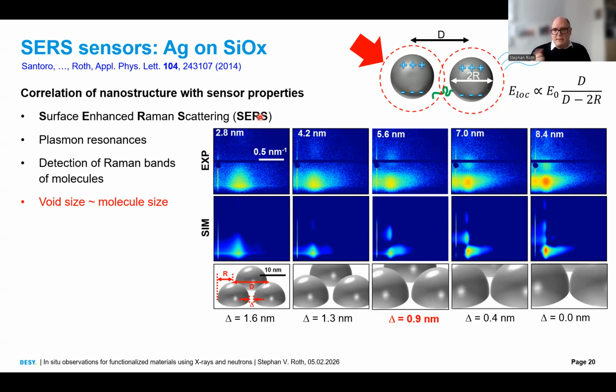And with this experiment, it's a straightforward experiment. We make an in situ experiment from 0 to 10 nanometer deposited silver on silicon. We know that the silver nanoclusters grow in a hemispherical structure. We know their structure from the island region up to the percolated region.